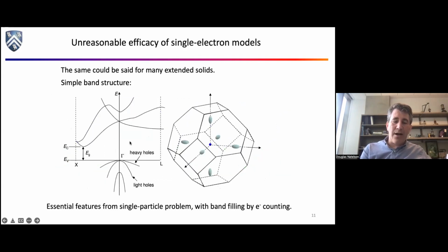The band structure looks a little more complicated for something like silicon. And so if you add a few more electrons than it needs to fill up the bands in silicon, you end up a little bit into what's called the conduction band in silicon. You end up with these little blobs in momentum space. That's where the electrons are living, in the conduction band, right? But you can get all of this for materials like silicon, gallium arsenide, the standard metals, germanium, all of these things you can understand very well without any electron-electron interactions in the problem at all, okay? If you want to get the fine details right, you have to account for them perturbatively, but you can get a lot of it without any interactions.